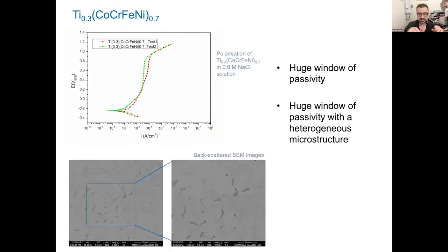Now, I've just picked these ones because what was amazing here is not so much that an alloy with titanium and chrome and nickel or something will give you a huge window of passivity, but coming from a background of steels, then aluminium alloys, then magnesium alloys, heterogeneous microstructures were generally known to be evil. So we started finding huge windows of passivities, even with multi-phase alloys.